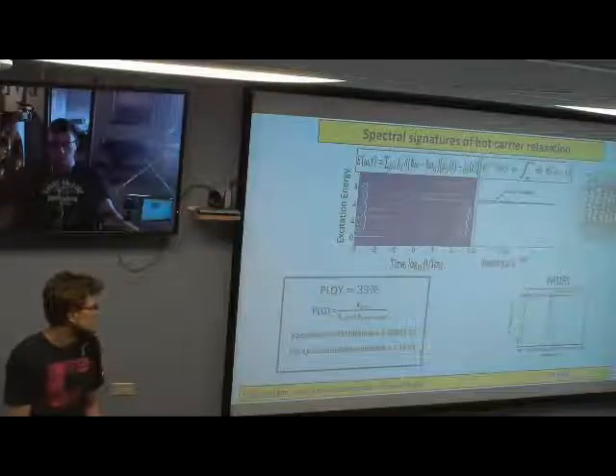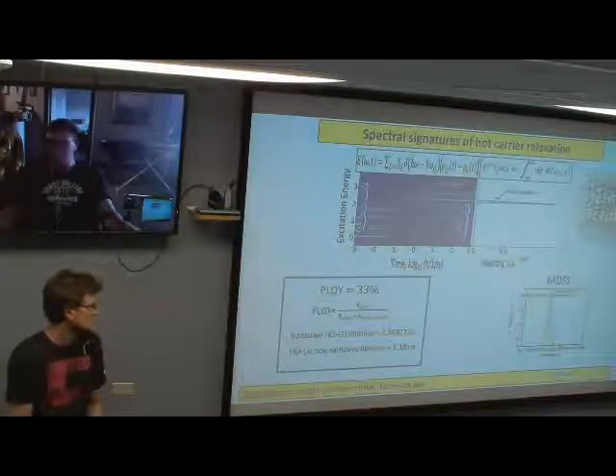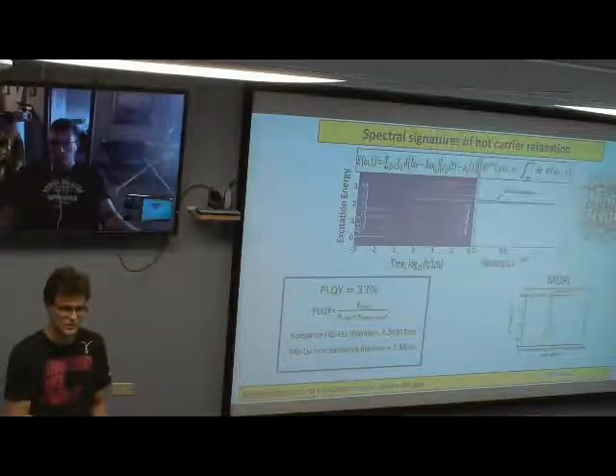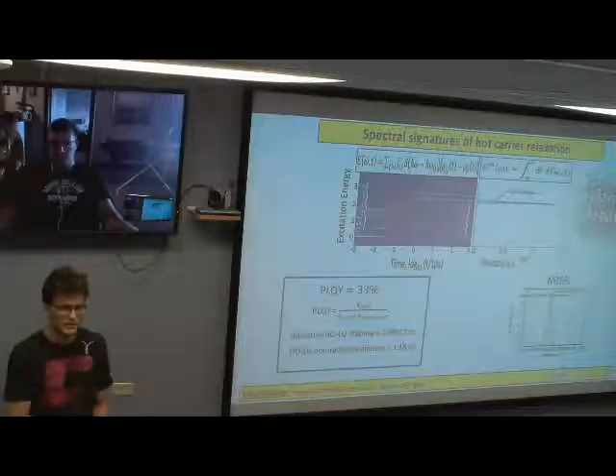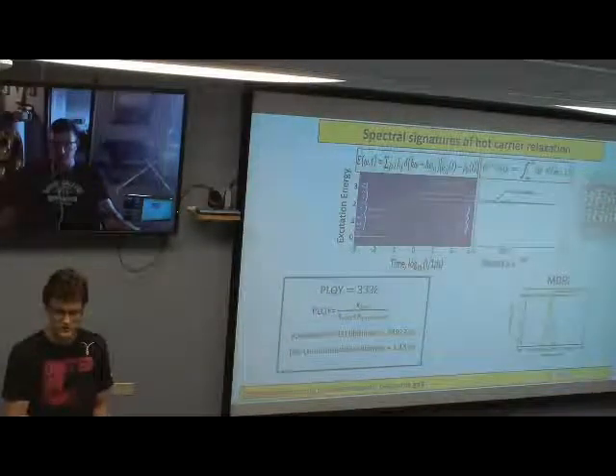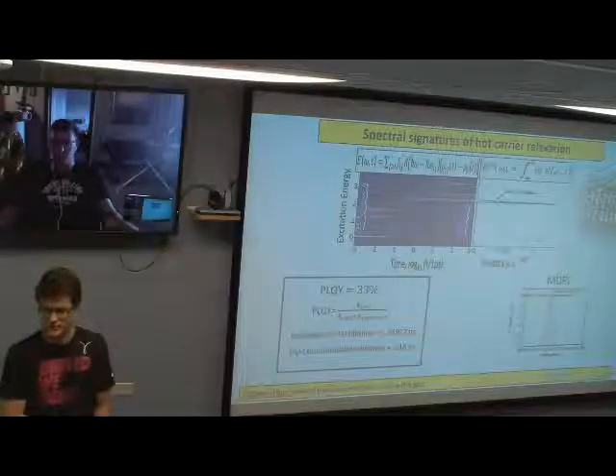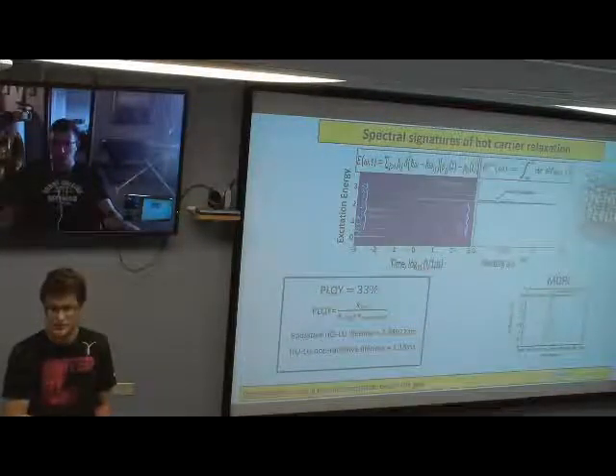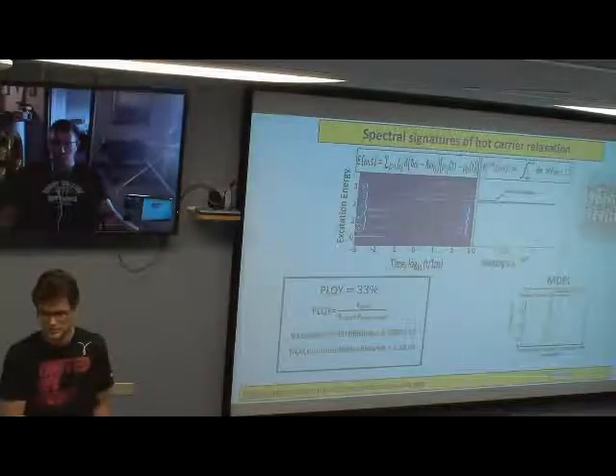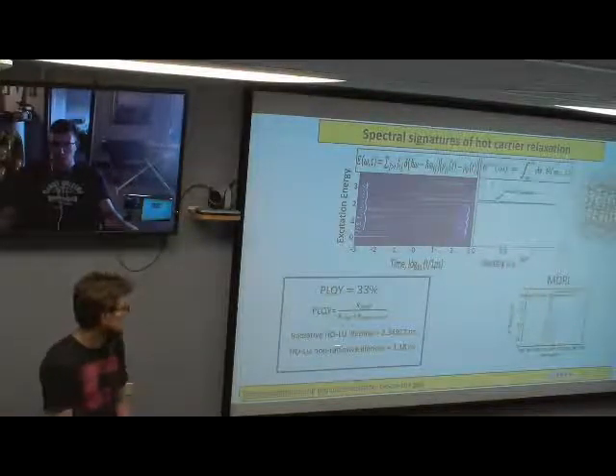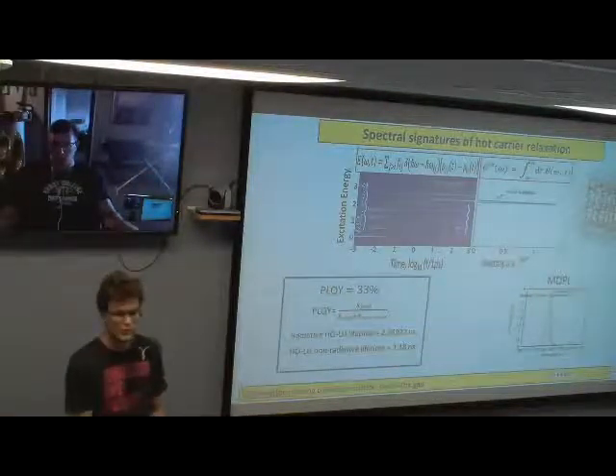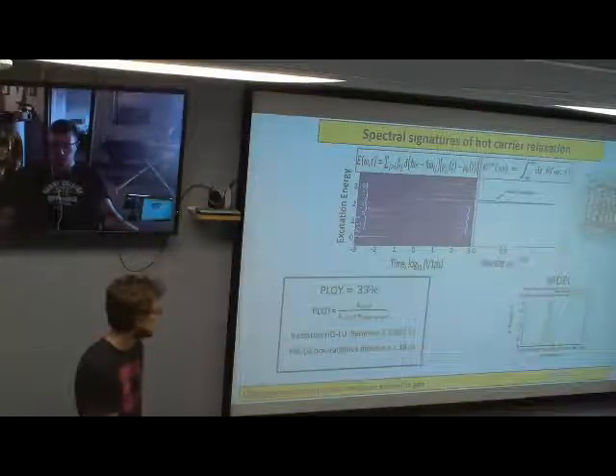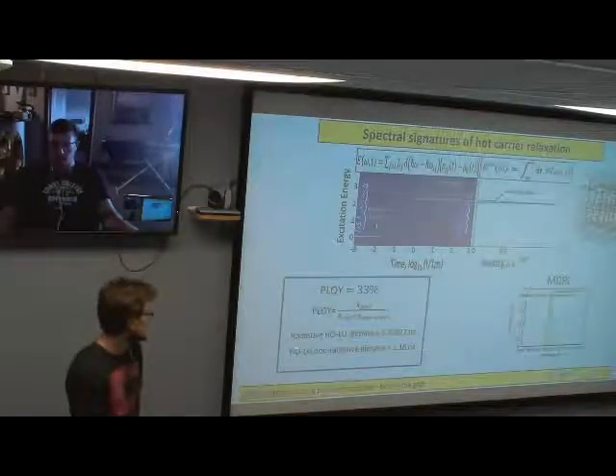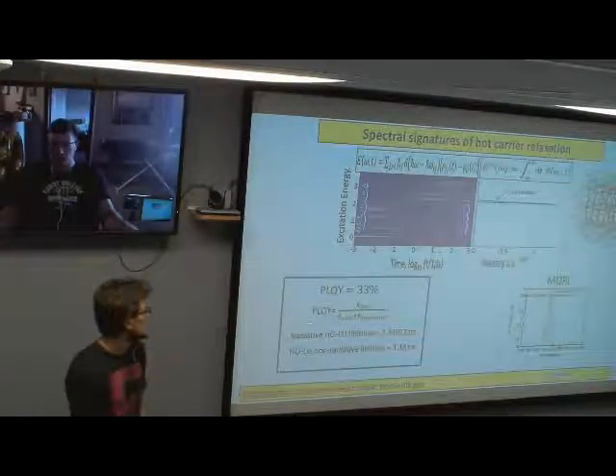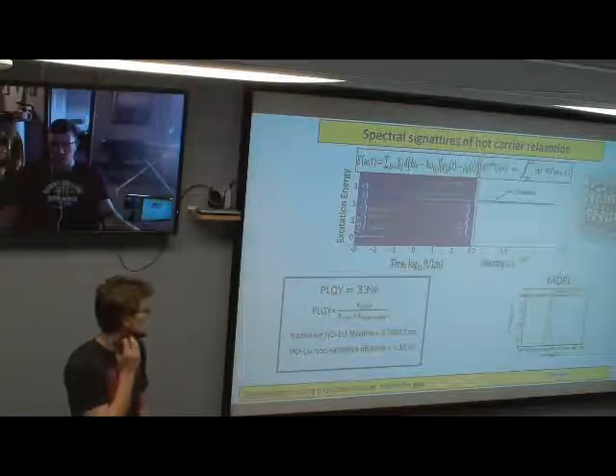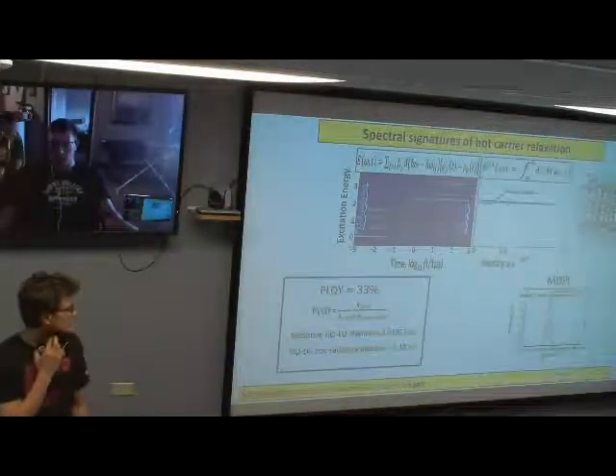If you go to super cool conditions, like 2 Kelvin measurements, they actually go to picosecond relaxation rates, like 250 picoseconds. Radiative, yeah. Which is interesting in itself. But we did these calculations for room temperature, or roughly room temperature, so these correspond pretty well, I think. I can't remember the non-radiative relaxation rates, but just from the physics, they're probably a little bit high